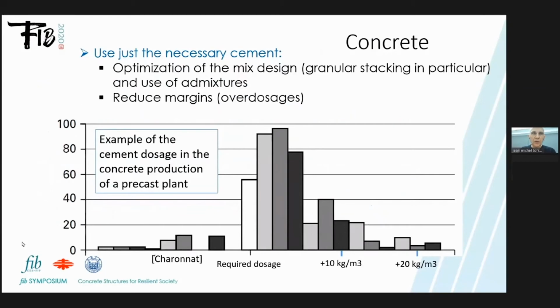That was for cement. On concrete, firstly, we have to optimize the mix design, with the granular stacking in particular, and the use of admixtures to reduce the quantity of paste for a given workability. And also something which is less discussed, we have to reduce margins, the overdosages. Here you have the dosage in the production of concrete for a precast plant, and you could see the required dosage was here. And in fact, they prepare concrete with a larger amount of cement, from, let's say, 0 to 20 kilograms of cement per cubic meter more than was required.